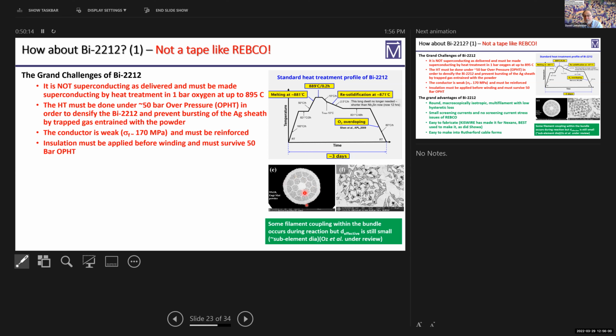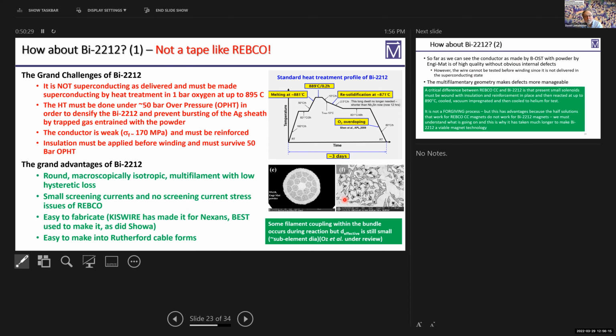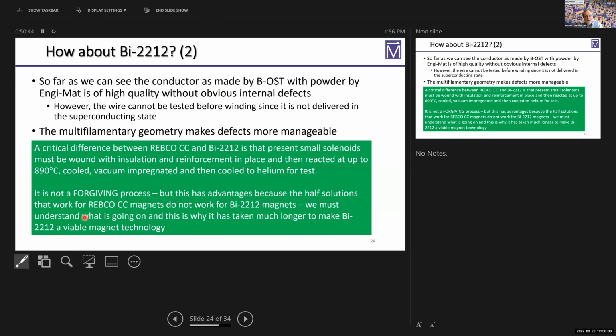So it looks actually like a niobium titanium or niobium tin conductor. And then after reaction, after having gone through the liquid state, there is some growth together of these filaments, and that has an effect. But the great advantages of all of this is that we have a round conductor, we can use Rutherford cables, it's macroscopically isotropic, it's multi-filament with a low hysteretic loss, small screening currents, and it's easy to fabricate. So all of these are good things.